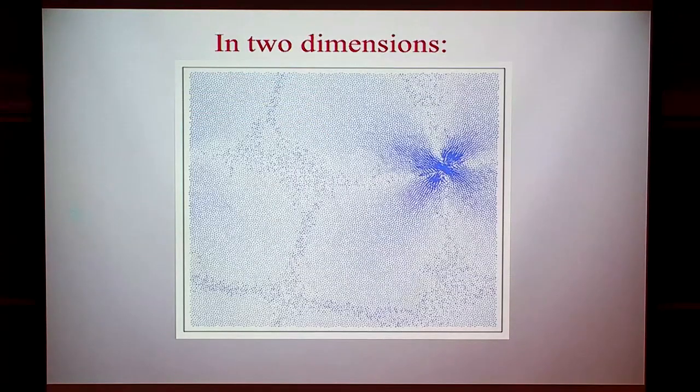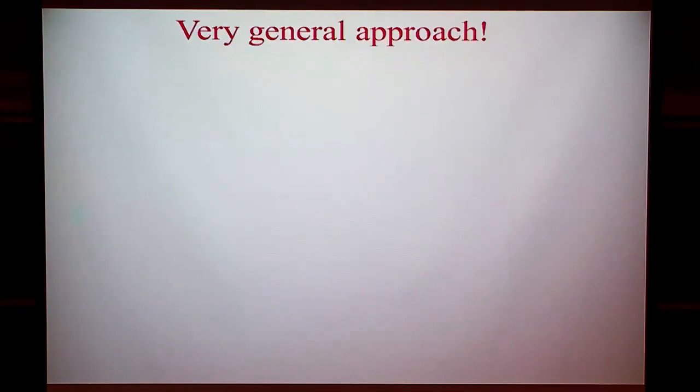So this is really the eigenfunction. You can find the matrix, you can diagonalize it, and what it does, it shows you the famous quadrupolar structure, that particles are streaming in and particles are streaming out. This is the displacement field, and whether you look at the displacement field or the eigenfunction, it's the same quantity. So this is indeed a plastic event, and you can understand what it does, but we'll make more statements about the analytic form in a second.